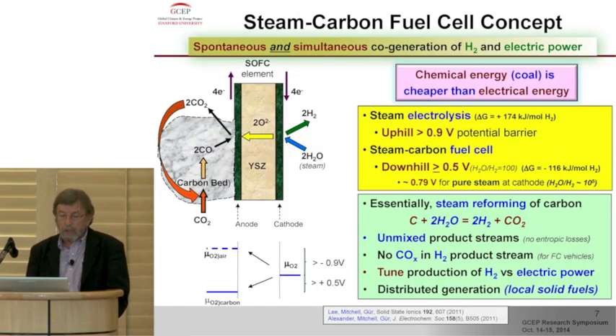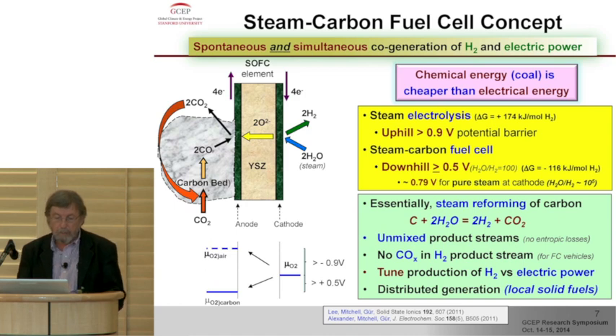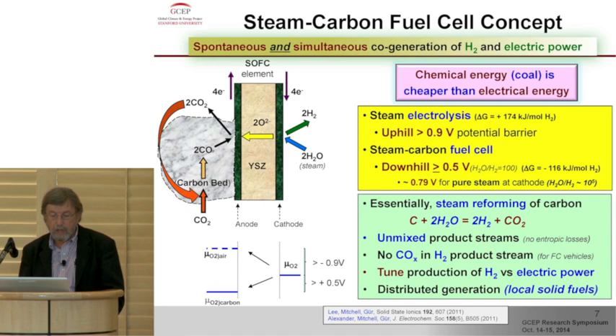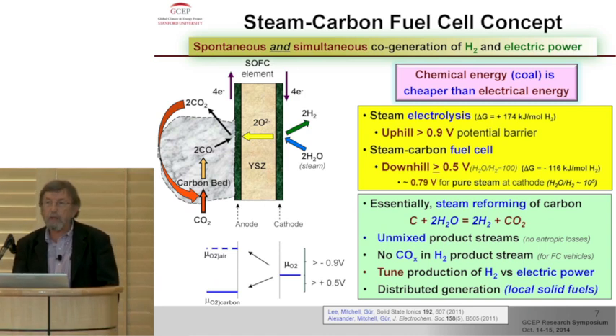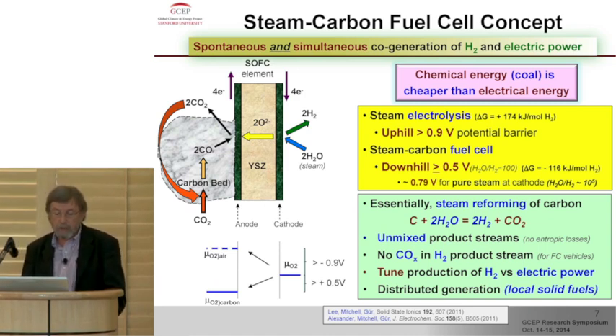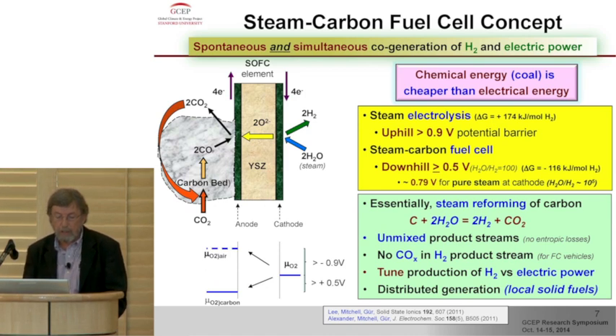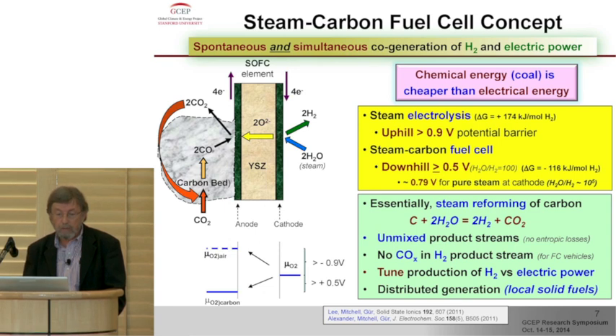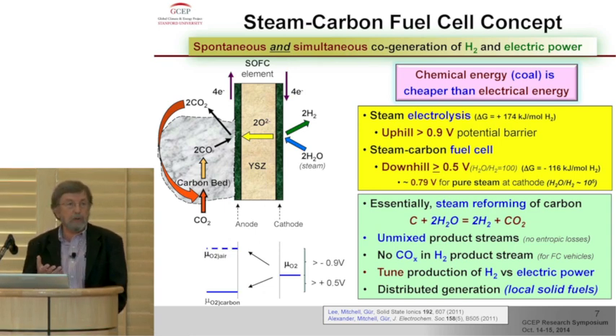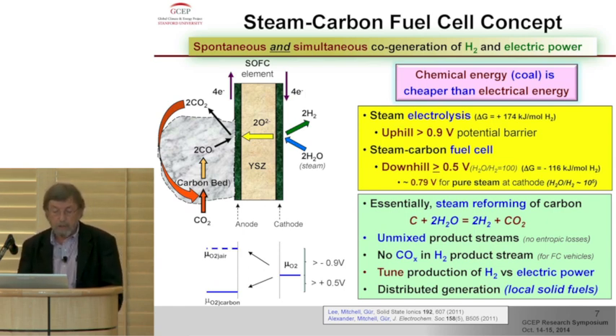Now, let me build upon this concept. Using the same platform, if we just replace the air side, or the cathode, with steam. So we have carbon on the anode side, we have steam on the cathode side. The oxygen activity difference between the steam and the carbon is a downhill gradient. So it's higher over here than it is over here. This provides a thermodynamic driving force of about half a volt or slightly higher than that, depending upon the temperature and the steam-hydrogen ratios.